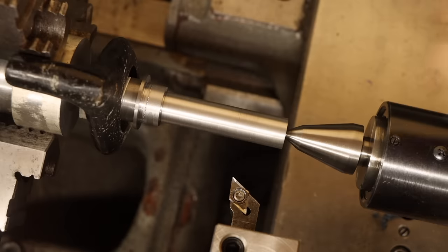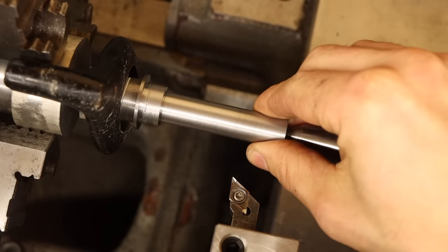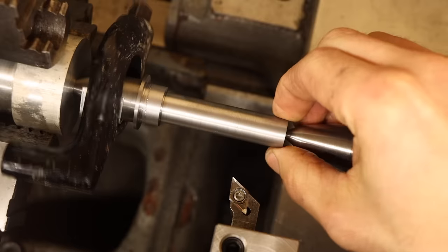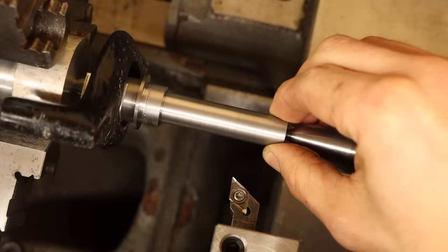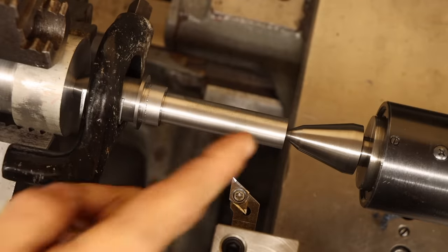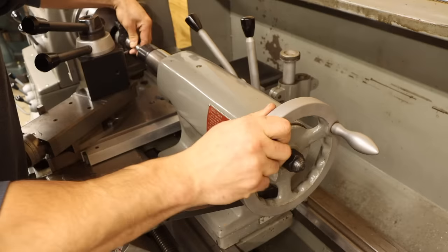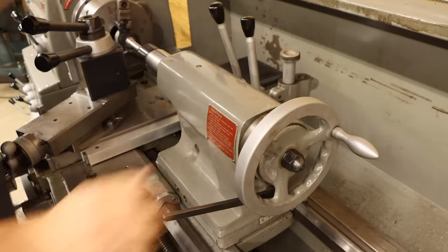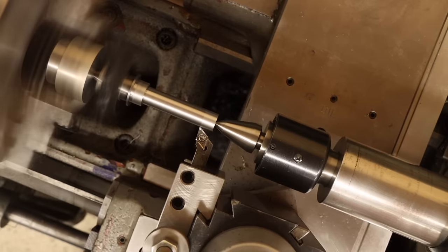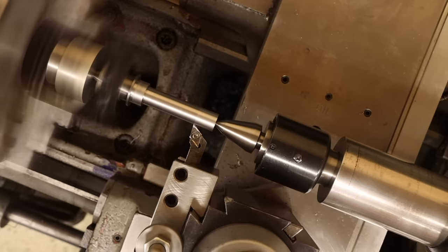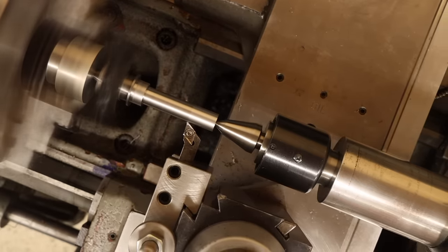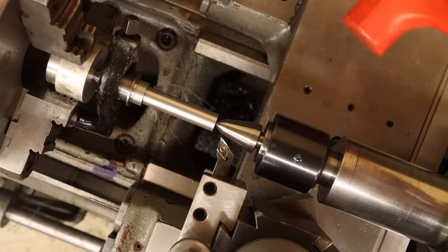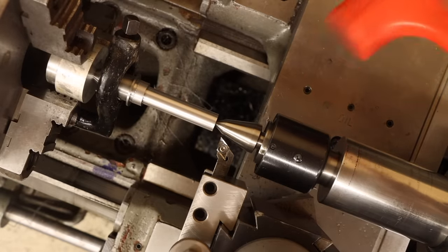I've got this main section pretty close to the final diameter, but I wanted to point out something first. That rattling is actually because the part shortened slightly as it cooled down. Not a big deal, just a good example of the importance of letting things cool before the final cuts. From here, I'm keeping the passes super light so deflection and heat aren't issues. And again, bumping out the small tailstock misalignments.